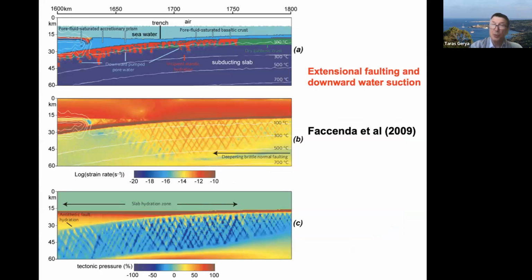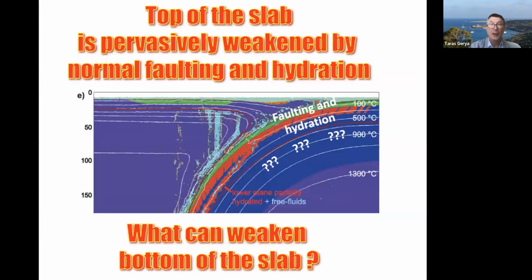There are some models, for example published by Manuele Faccenda back in 2009, where he suggested that deviatoric stresses can be large enough to cause downward water suction. This is, however, a matter of debate, because Jun Korenaga argued against it and rather suggested that it's cracking of plates rather than water suction that is causing the seismic velocity anomalies. But what is not denied is this pervasive damage of plates by normal faulting that occurs at trenches, because we see these observables almost everywhere. And of course, the structures penetrate deep into the slab interior. So the top of the slab can be irreversibly weakened by this brittle faulting and presumable hydration and cracking.